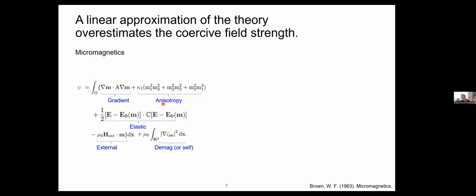A distinguishing feature of this theory is that it very neatly brings together the different energy terms that play a role in magnetization reversal. If you start, for example, with the anisotropy energy, the constant that I was referring to, which plays an important role in this reversal. Here is a cartoon that shows a unit cell with three different crystallographic directions, and the blue arrow here schematically indicates that this material likes to magnetize along one crystallographic direction. What the anisotropy constant does is, the magnitude of this constant tells how much energy penalty we are going to pay if we try to rotate this magnetization away from what is called its easy axis. And this energy penalty is quantified by this term.